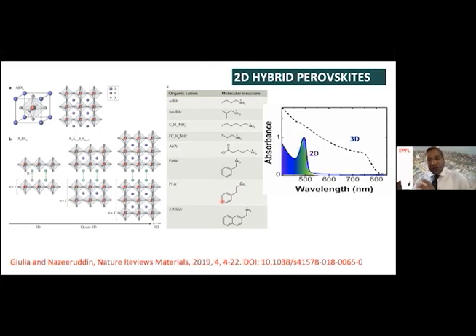Now let's go to the properties of these two materials. Three-dimensional perovskite, we have discussed, absorbs up to 800 nanometers, the black dashed line. Now, if we replace this cation with one of these bigger organic cations, it forms a two-dimensional perovskite. If you compare and contrast the absorption spectral properties of the three-dimensional and two-dimensional perovskite, on the right side of the panel, the two-dimensional perovskite absorbs only up to 500 nanometers.